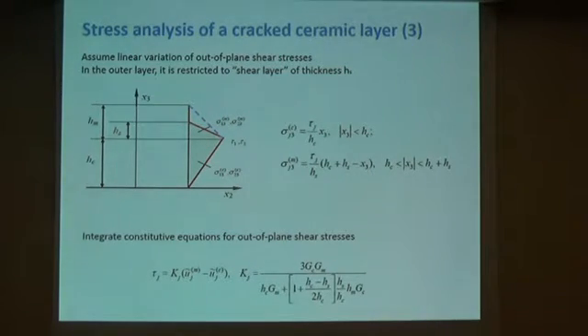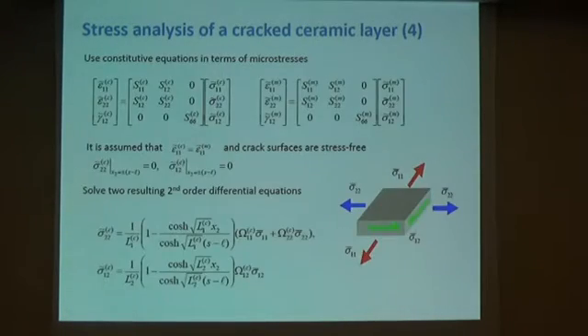So to solve equilibrium equations, we need to make an assumption about these interface shear stresses. So we assume that out-of-plane shear stresses vary linearly through the thickness of ceramic layer and metal layer. But we also assume that in the outer metal layer, this variation of out-of-plane shear stresses is restricted to the shear layer. So it is non-zero here and then zero in the outer portion of the metal layer. So this is how it's written in mathematical way. And this allows us to integrate the constitutive equation and obtain expressions for out-of-plane shear stresses tau in terms of coefficients k, shear-lag parameters, and in-plane displacements in the metal and ceramic layer.